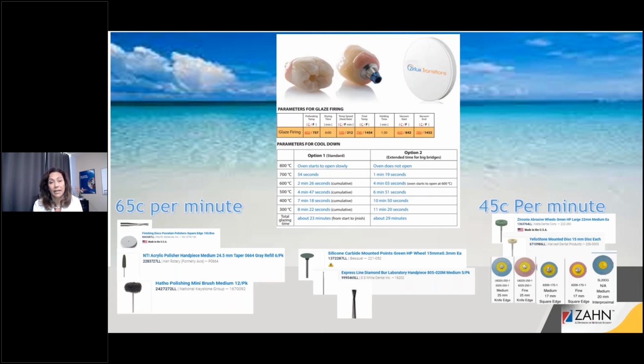And if you really want to get in there and make a difference and not have to touch that unit very much at all after it's sintered, which I highly recommend, the less you need to grind on the unit, the better. You don't have to worry about creating heat fractures. I do like the NTI acrylic polisher. You can just kind of go around the surface. If there's any lines, parting lines that you need to smooth out, that works great. Along with the little medium Scotch-Brite brush there on the bottom left.